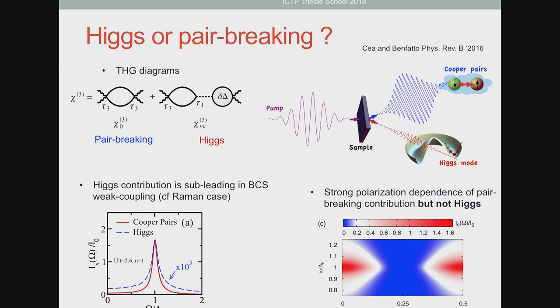If you take just a very simple model, square lattice with nearest neighbor hopping, you can actually compute the polarization dependence of the signal. What you realize is that the Higgs mode contribution is essentially independent of the angle of the incoming light with respect to the axis, whereas the pair breaking contribution is very strongly dependent on your incoming polarization. And this we know, for example, from Raman scattering calculations, that such a response is going to depend very much on the kind of light polarization that you use.